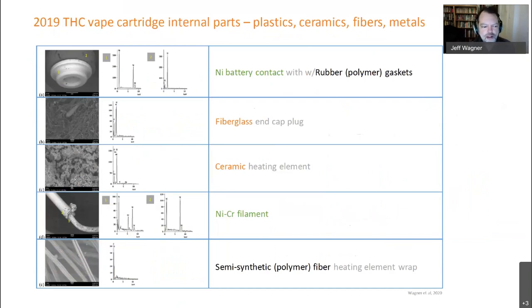So the battery contact and filaments were nickel-based with some chromium. And with SEM, we could get nice spatial resolution, sometimes even seeing different chemical compositions at different parts of the filament and wire leads, as well as fiberglass, ceramics, and on the bottom, you see this morphology typical of a semi-synthetic polymer fiber, such as rayon, that was used to wrap around the heating element. In the upper image, there's also an example of the kind of rubbery polymer gaskets that we found in a lot of these devices.